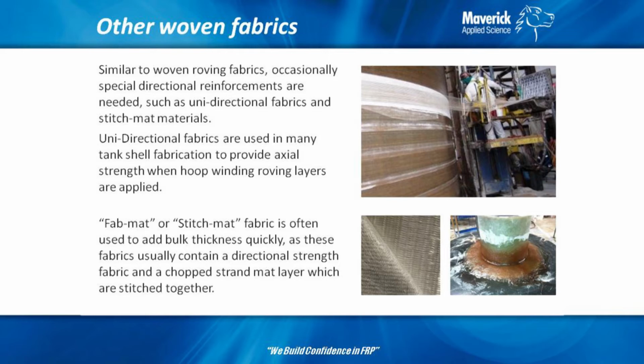Fab mats and stitch mats, we don't typically recommend because they can become very difficult to wet out. As you see with this, you basically have a chop strand mat and a woven roving attached to each other, stitched together. The amount of resin it takes to wet that out, both sides, is not common. So a lot of fabricators end up putting some of that on dry. Dry will leave you voids. Voids are bad in fiberglass.